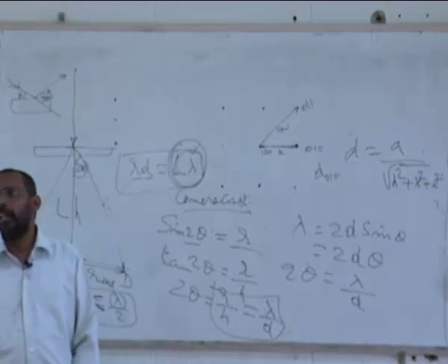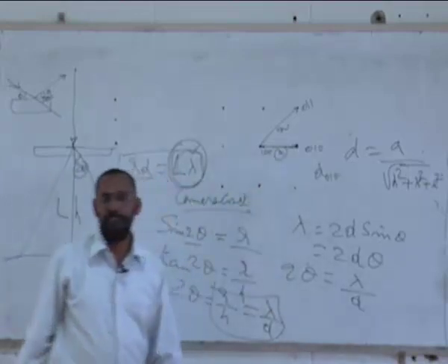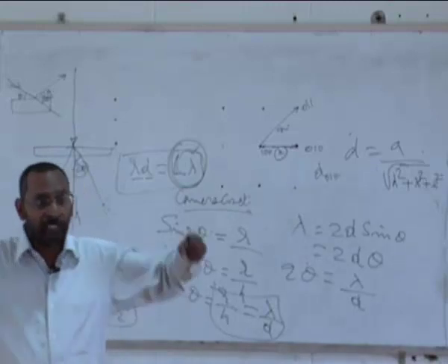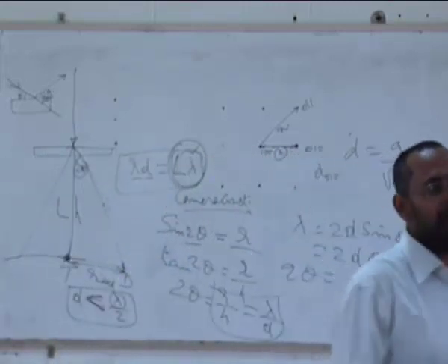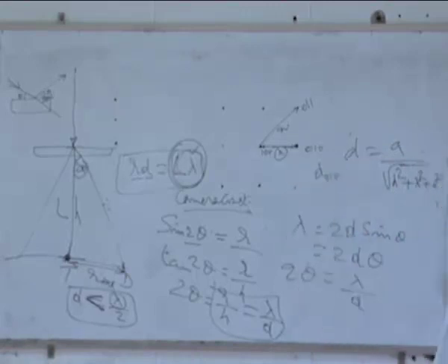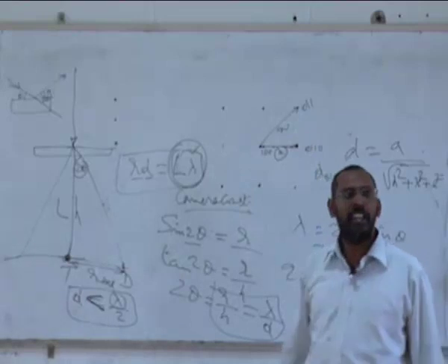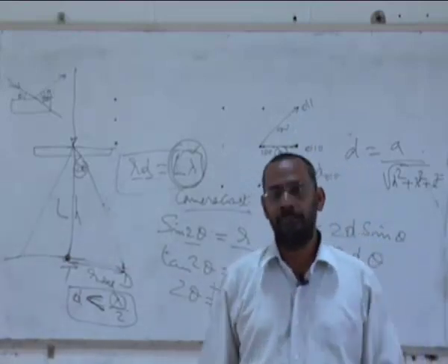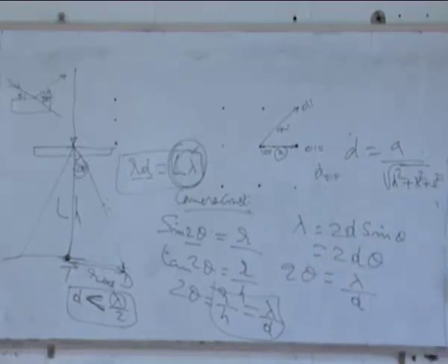How accurate my lambda is, and how accurately I have measured this R. This R I am physically measuring, right? So if my accuracy there is at the third decimal, then I may be able to get a third decimal accuracy, let's say, in A, otherwise I will not. And that is where I was telling you the precision lattice parameter calculations which we talk about in X-ray diffraction